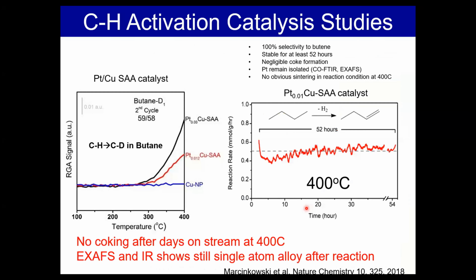So this is now taking butane, sort of shale gas analog, and running it over the 1% platinum copper single atom alloy catalyst in gas flow in the reactor. And you can see at 400 Celsius, that catalyst is stable on stream for 2 days in converting butane to butene and hydrogen. And we don't observe any coking.